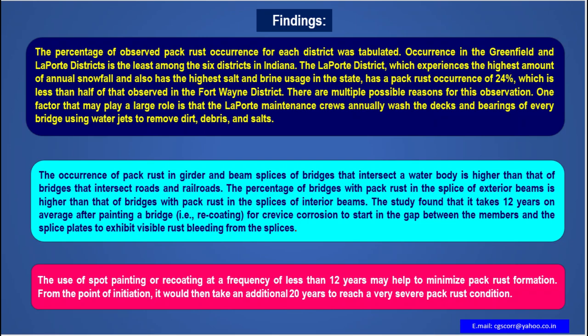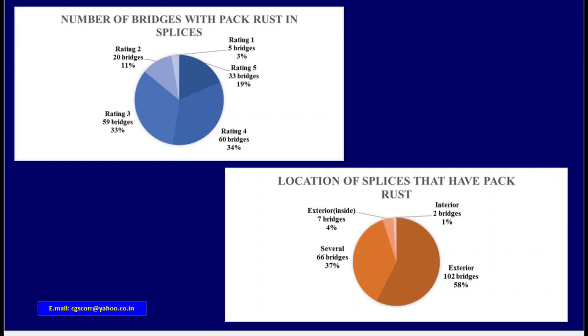The study found that it takes 12 years on average after painting a bridge, that is recoating, for crevice corrosion to start in the gap between the members and the splice plates to exhibit visible rust bleeding from the splices. The use of spot painting or recoating at a frequency of less than 12 years may help to minimize pack rust formation. From the point of initiation, it would then take an additional 20 years to reach very severe pack rust corrosion.